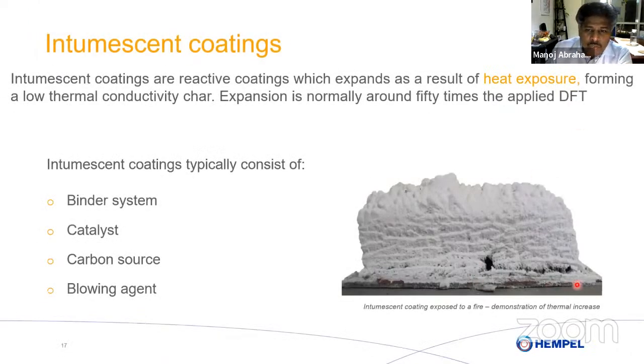So what basically happens here is that you have your steel, there is a primer applied, and then the intumescent is applied. As the temperature increases, typically the binder system is used to spread the coating, right? Typically for a cellulosic intumescent coating, you will have an acrylic binder, say a water-based binder or a solvent-based binder. And then you have a catalyst like ammonium polyphosphate. When the steel reaches a temperature of 200 degrees centigrade, the catalyst triggers an acid reaction, and slowly this carbon source, a material like pentaerythritol, starts to give out carbon.